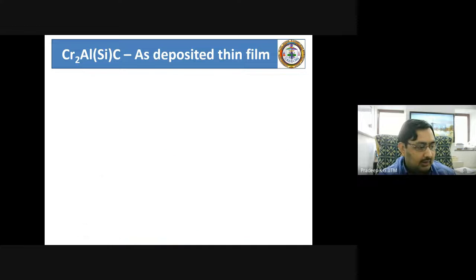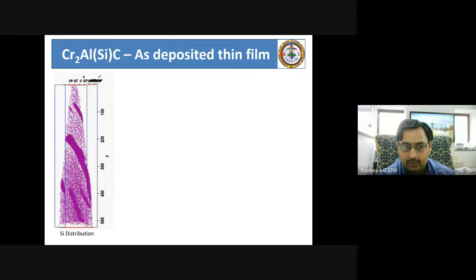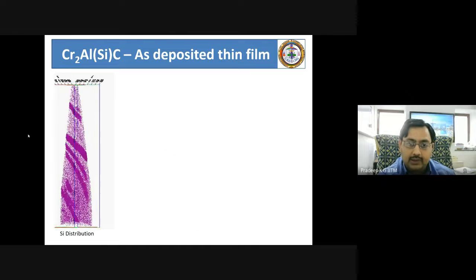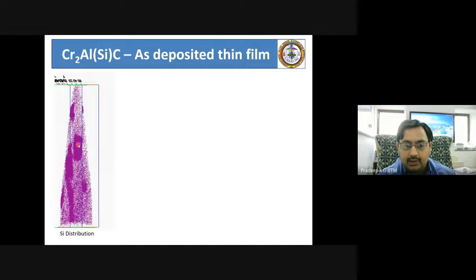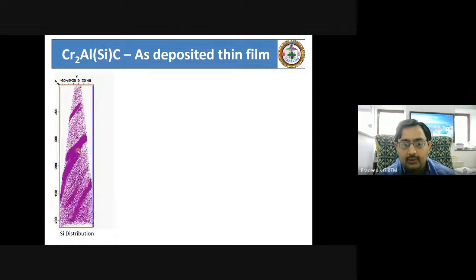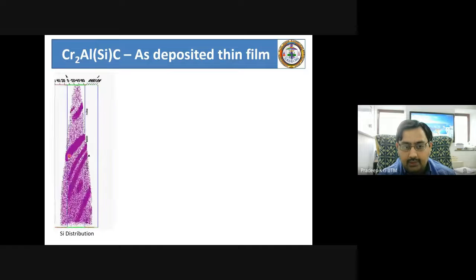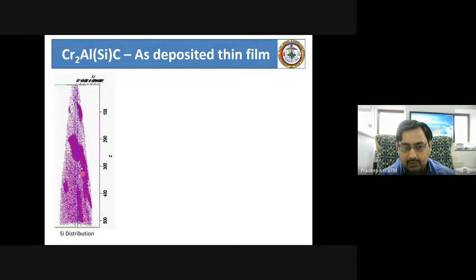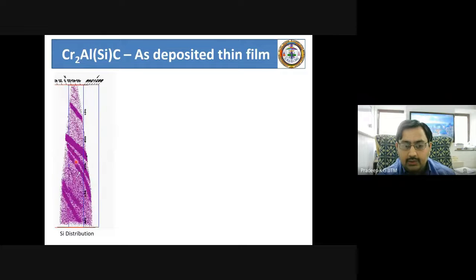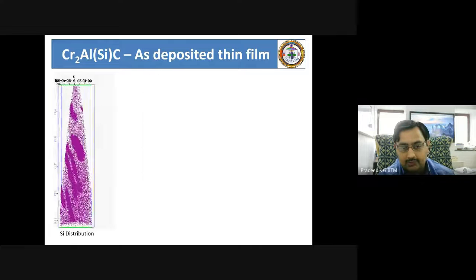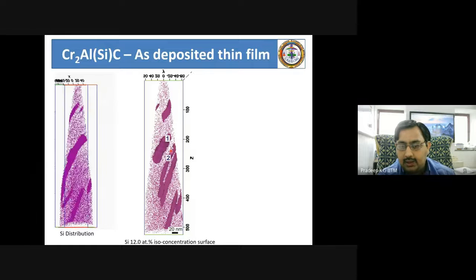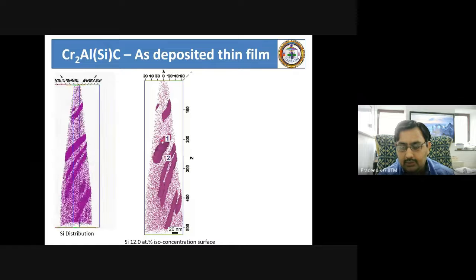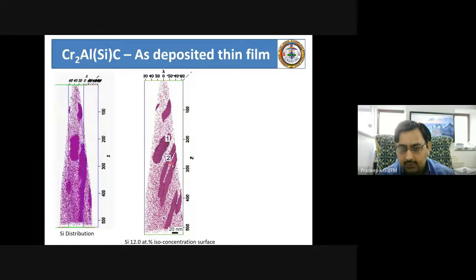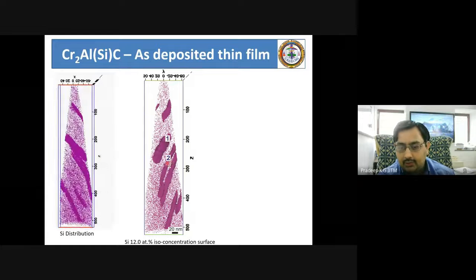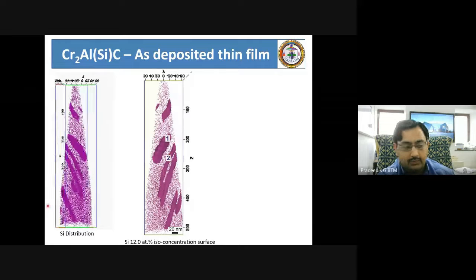You take the same needle and then you look at this in atom probe tomography, then you are able to see that there is silicon distribution in a more inhomogeneous way, and there are nanoscale laminar microstructures visible in a 3-dimensional volume. But within the nanoscale microstructure, you have variations. That means there are some types of precipitate which are broader in width and longer, but there are some other types of precipitate which are narrower in width, but extremely longer.